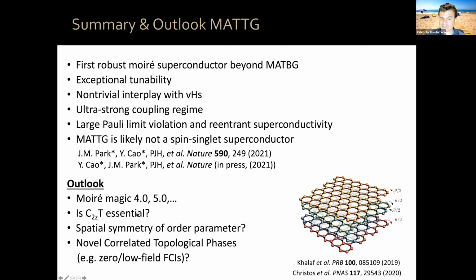Okay, if this is essential and if this theory is correct, then other theories that also like the C2T symmetry, but in this particular theory, this superconductivity is very similar to the mechanism for the bilayer, trilayer, etc., and it's due only to electron-electron interactions, and it's called the skyrmionic theory of superconductivity. Your Cooper pairs are actually a Bose condensate of skyrmion pairs in the system. So it's a pretty exotic mechanism for superconductivity. It remains to be seen if that's the mechanism.